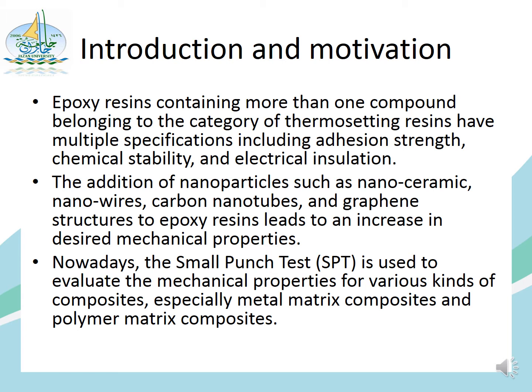These characteristics are reflected as an advantage in increasing the resistance of the composites, also including the wear rate compared to large particles, and this type of nanoparticle can yield a layer of strong film that blends with wear debris or other kinds of mechanical properties. Also, various evaluation techniques were used to evaluate the tensile properties. Also, we can tell that the tensile properties, flexural properties, and tribological properties for such composites are evaluated using conventional techniques.